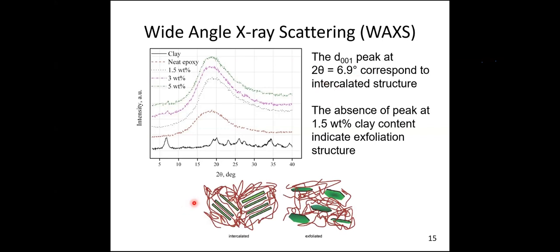If you see my laser pointer, this left hand side is the intercalated structure. Because of higher clay content, the clay is not mixed well with the epoxy. If you see, it is arranged in some parallel fashion. It is in an agglomerated state. So higher the clay content, you get this kind of agglomeration. Whereas, if you see, this is an exfoliated structure. Again, for 1.5 there is no peak, which indicates that the clay is mixed well with the epoxy. That means the distance between 2 layers is more than 1.28 nanometer. So that is the meaning, that it is dispersed well. So from the XRD, we were able to confirm that 1.5% clay is dispersed well with the epoxy.